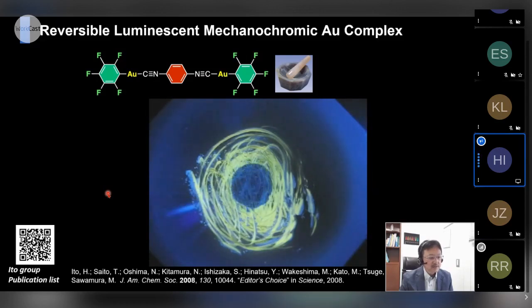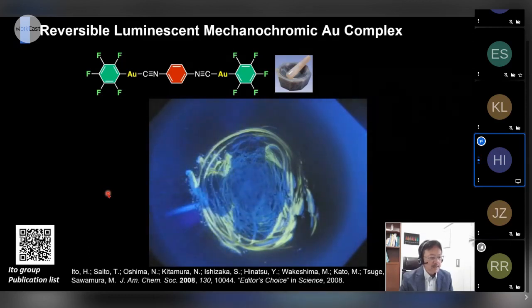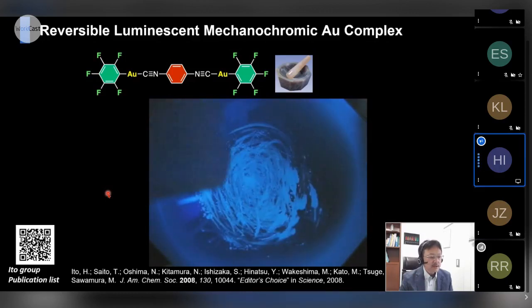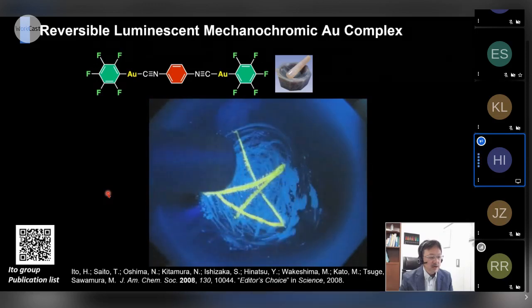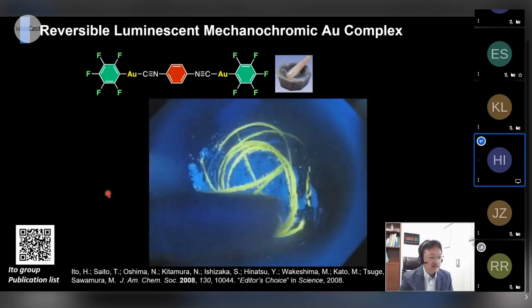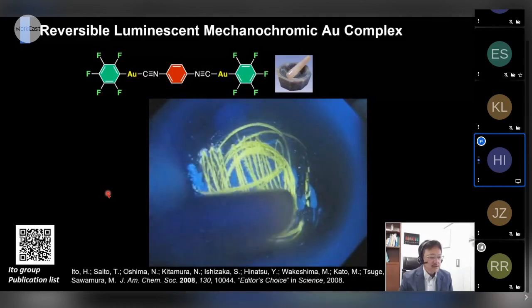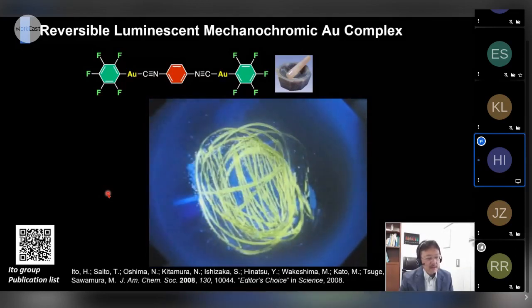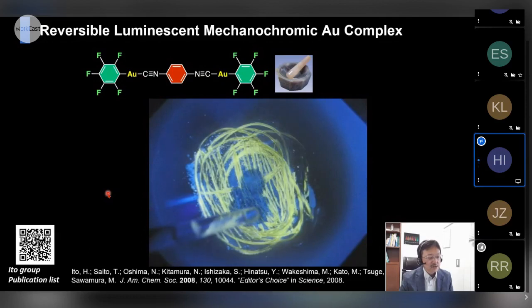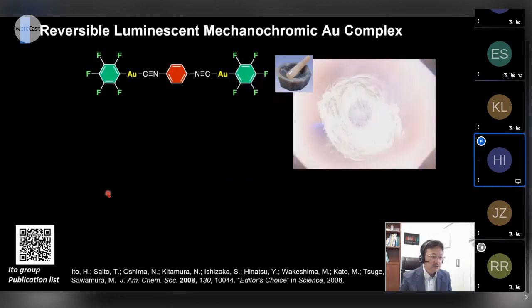The interesting thing is, if you add solvent on the surface of the yellow colored area, you can see that the yellow color is rapidly reverted to the original blue color. And if you add the solvent and evaporate it, you can change the blue color to yellow again. You can enjoy this color change repeatedly. We have already checked that this color change can be repeated at least 20 times without any color degradation.